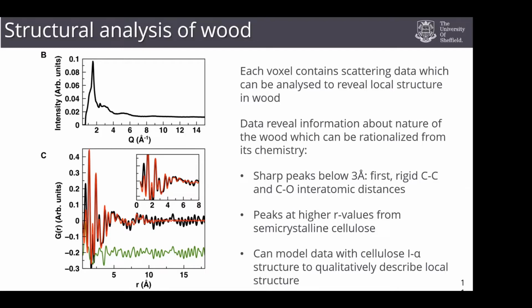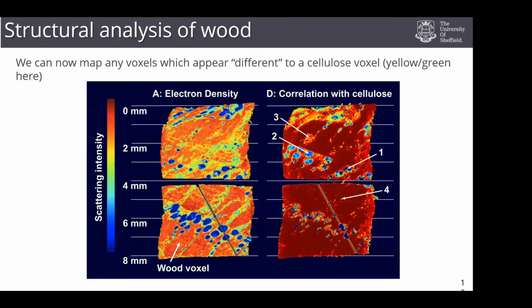But what this tells us and what we can do is fit these data sets with a model that we know is true for cellulose, for wood. And we can actually tell that this is the cellulose structure. So now we know what the structure of wood in the Mary Rose sample looks like. So if we know what wood looks like, we can figure out what not wood looks like, if that makes sense. So we're on the hunt now for things that could damage Mary Rose wood. And that's what this is showing you.